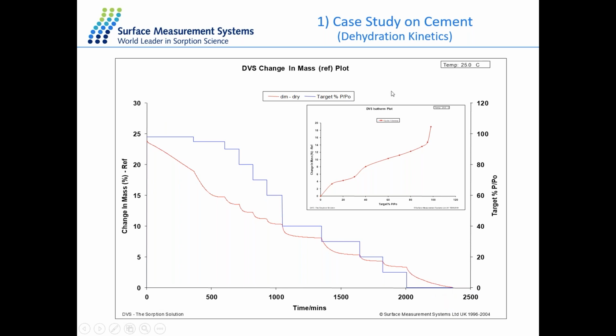And this plot is the corresponding isotherm for the mass plot. So you can see at different steps, it shows different kinetics. Some of the steps are quite long, and some of the steps reach equilibrium very quickly. And it also indicates that dehydration is occurring in different steps. For example, here there's a rapid mass loss at 90% RH, which is most likely due to the loss of loosely bound water.